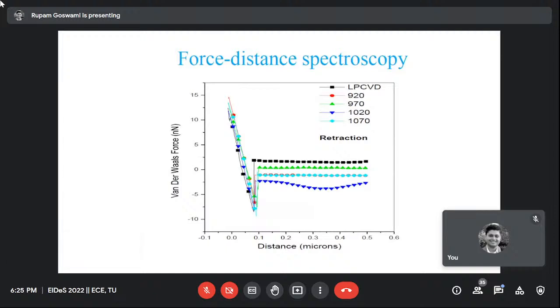Okay. So the purpose of showing all this work is that technologically we can bring the required changes in the active layer. Particularly in this one, you can see that when we anneal the polysilicon film at different temperatures, there is the grain growth mechanism, called the normal grain growth mechanism. Here undoped polysilicon is annealed at different temperatures, and the unannealed, as-deposited polysilicon is also there. This dip in force distance spectroscopy using AFM gives the information about the surface energy of the grain, and this surface energy of the grain has direct relevance to the piezoresistive coefficient of the film.